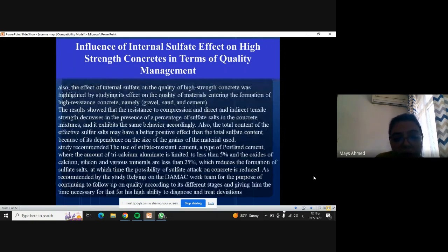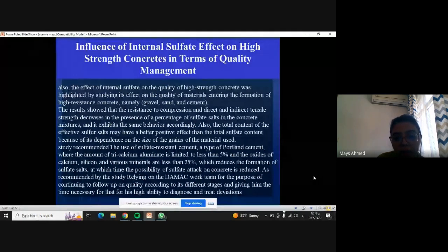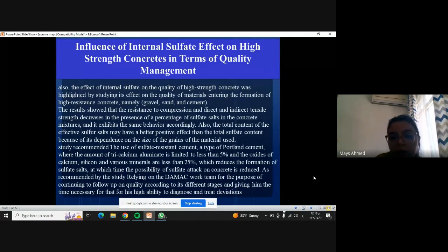Also, the effect of internal sulfate on the quality of high-strength concrete was highlighted by studying its effect on the quality of materials entering the formation of high-resistance concrete, normally what is contained is gravel, sand, and cement. The results showed that the resistance to compression and direct and indirect tensile strength decrease with the percentage of sulfate salt in the concrete mixture, and it exhibits the same behavior accordingly.